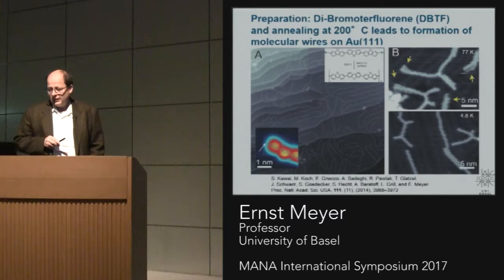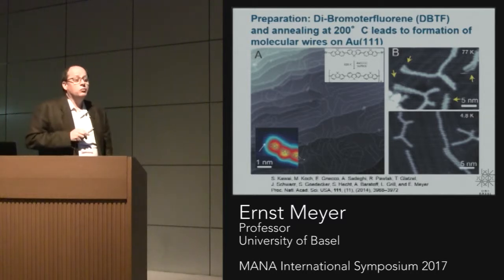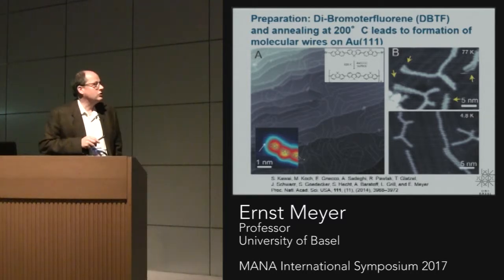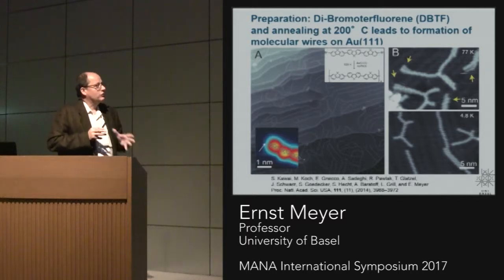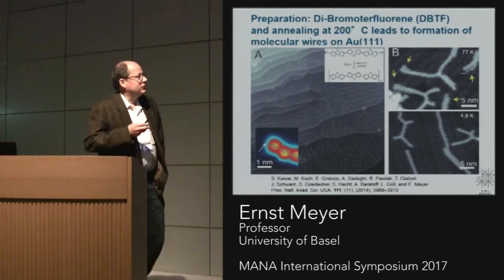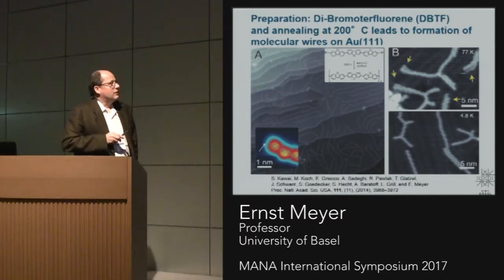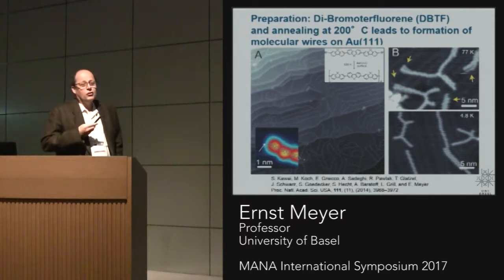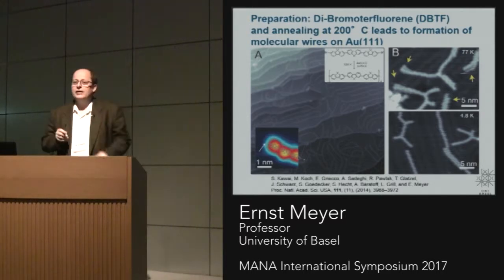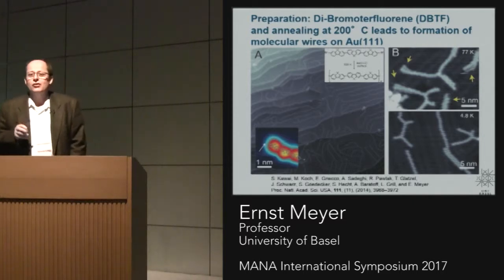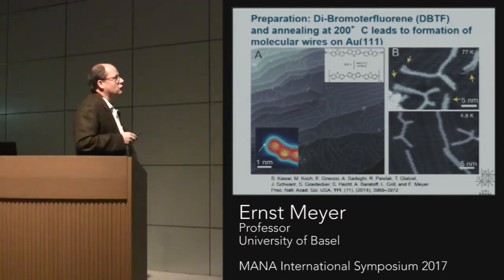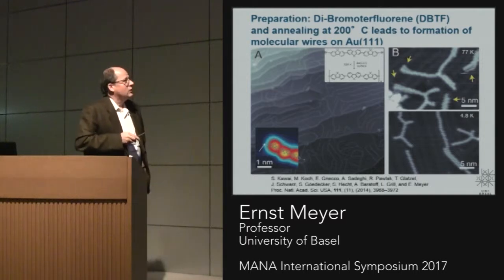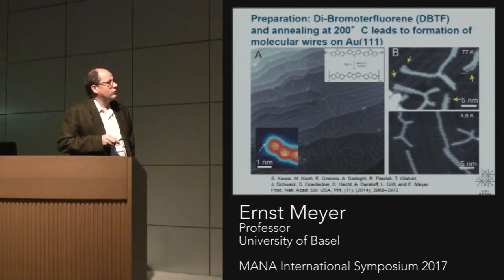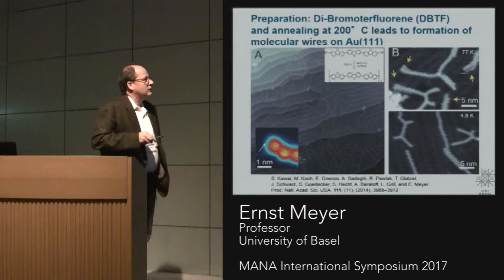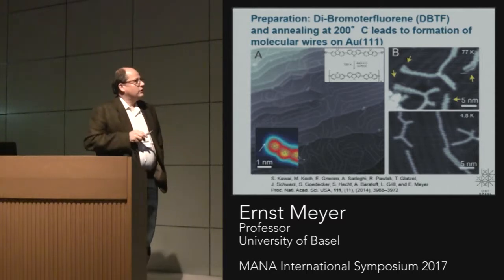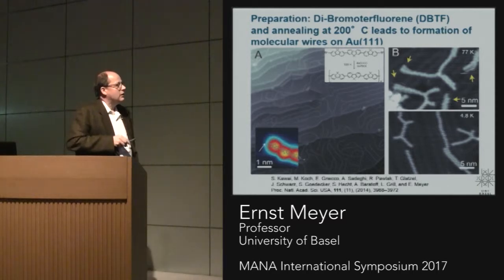So the method to prepare this polymeric wire under vacuum conditions is of course not so trivial, because you cannot simply evaporate them. And so actually the most elegant way to really prepare very clean material which never saw any air or any humidity or any contamination is to evaporate a precursor, a monomer in that sense. That's this guy here. You evaporate it and afterwards you anneal it.